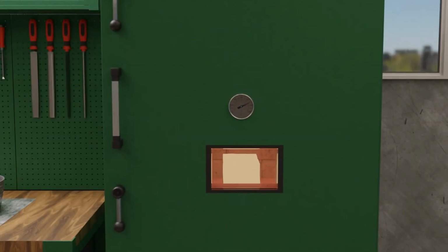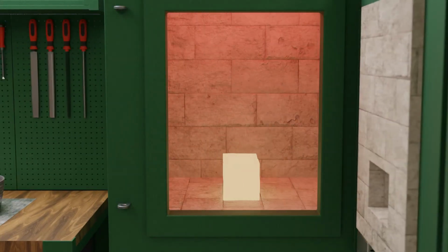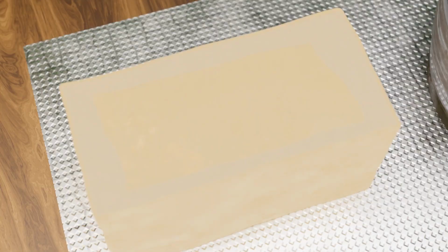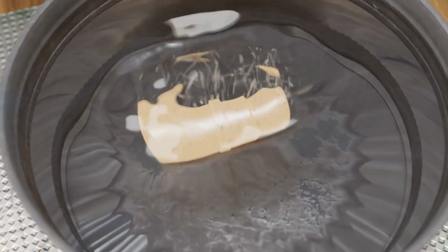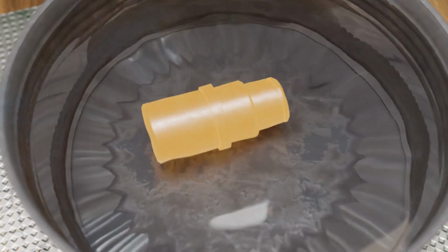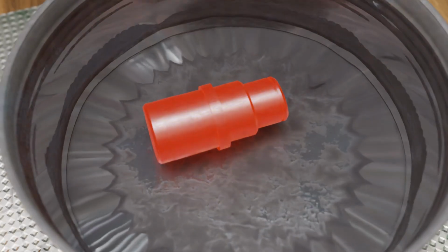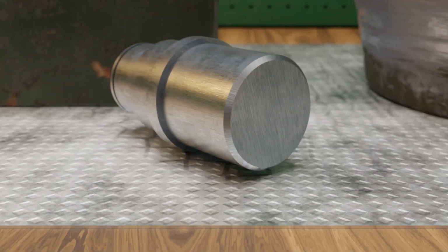After carburizing the surface layer, the actual hardening takes place by quenching the component in water or in another quenching medium. Depending on the process control, the steel is quenched directly after carburizing, which is referred to as direct hardening, or the steel is first cooled slowly in air after carburizing and the hardening process is carried out subsequently. After case hardening, tempering is generally required to reduce the high residual stresses caused by the large hardness differences between the surface and the core of the component.